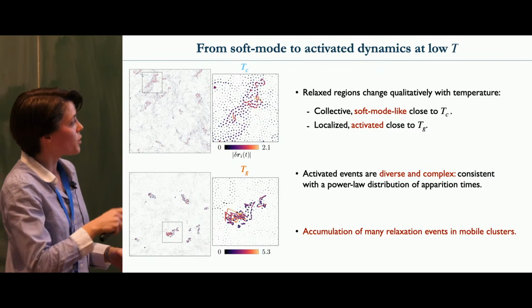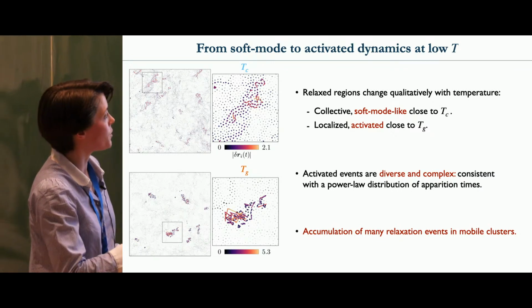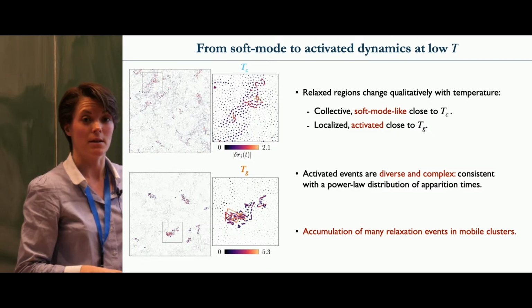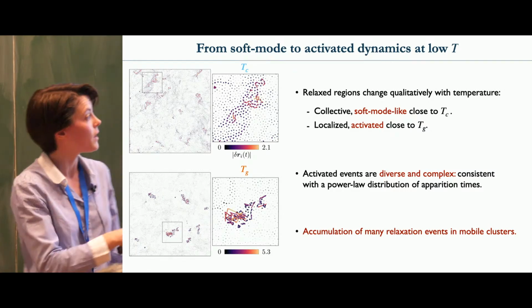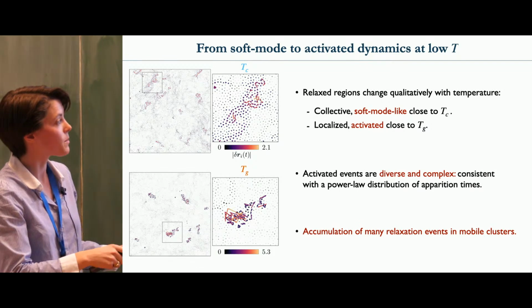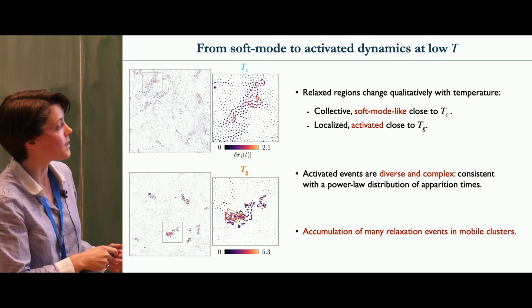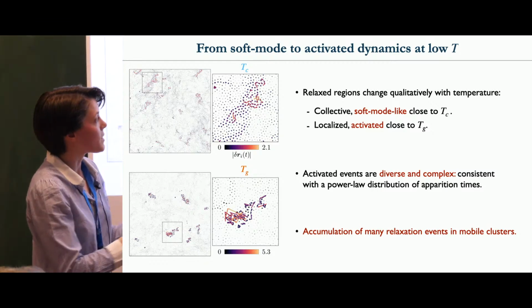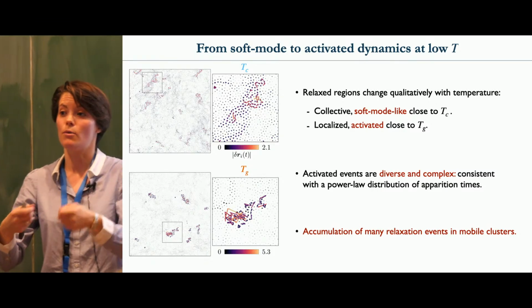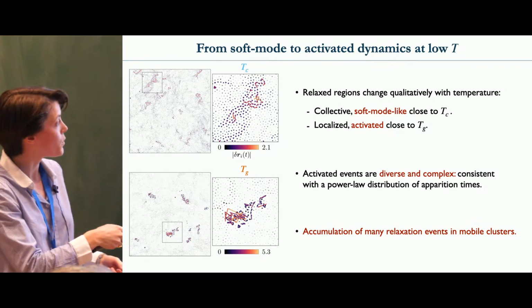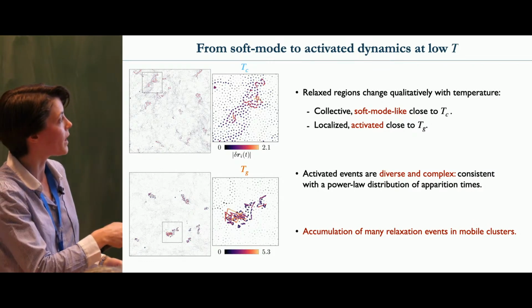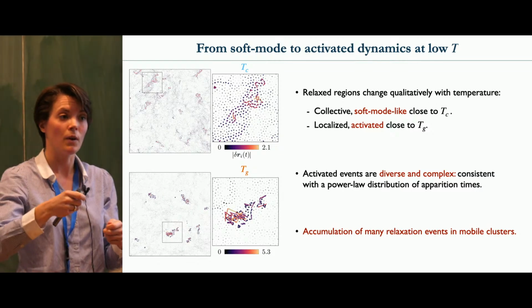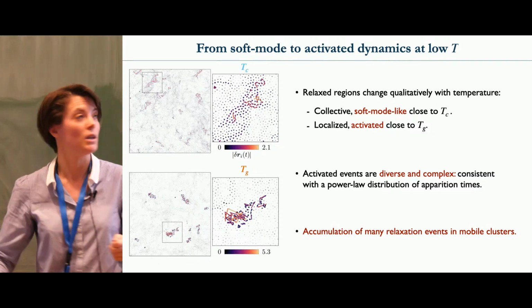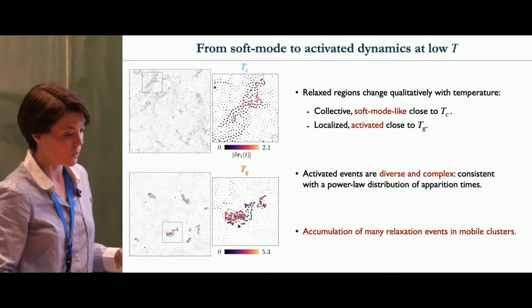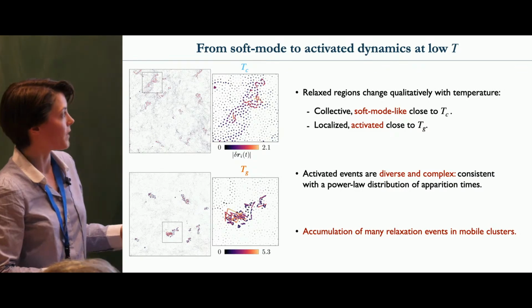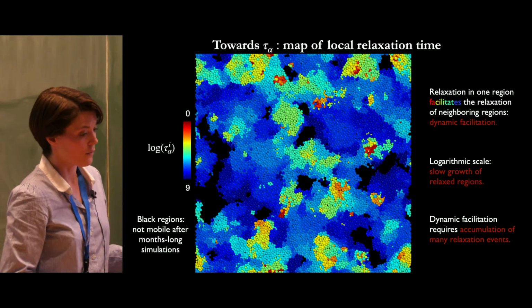While at much lower temperature, in these mobile regions, you have much more complicated relaxation events. I think you would agree with me that this corresponds to highly complicated moves, and to get to this point, the system had many relaxation events that give rise to this huge displacement. So particles here move 5 diameters apart, but this happened by the accumulation of many relaxation events, while here there may be 1 or 2. This is a point that I want to describe a bit afterwards.